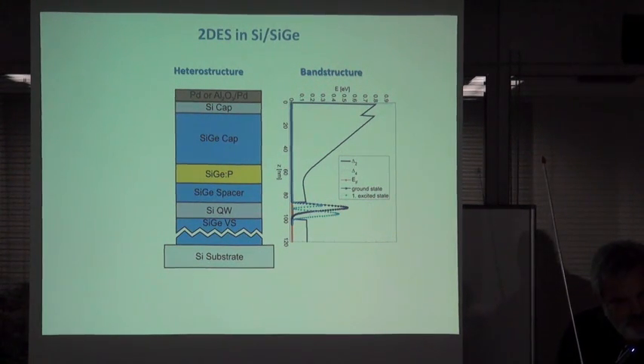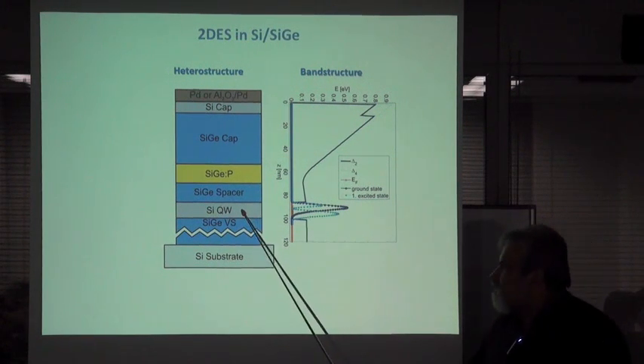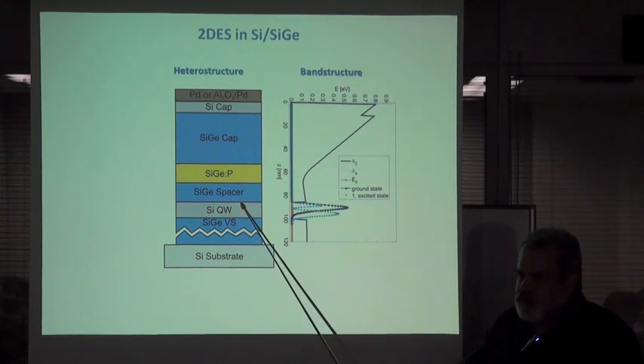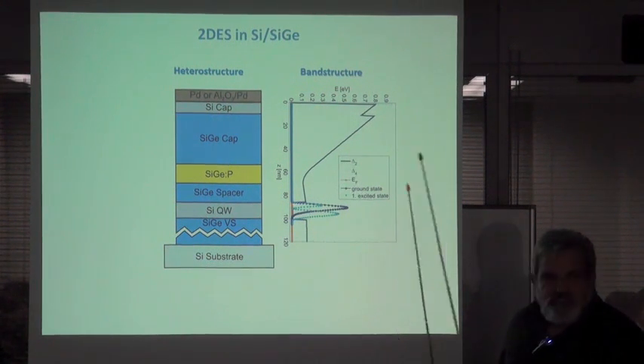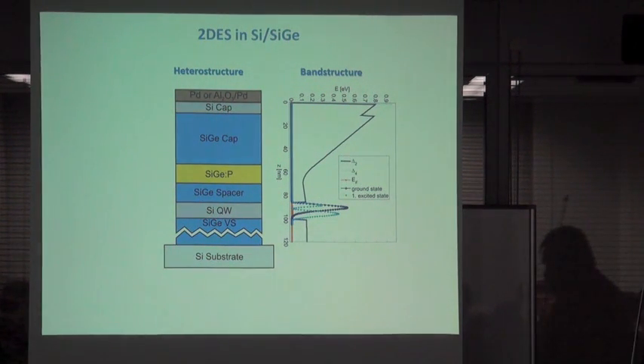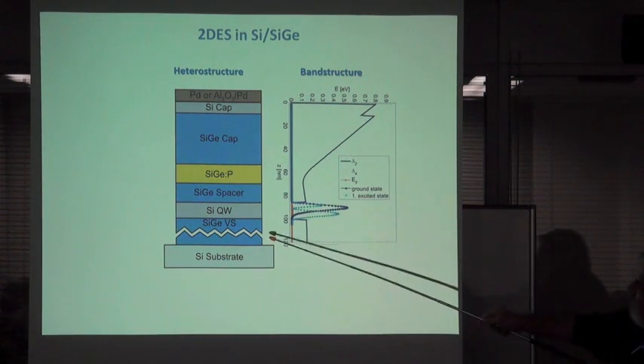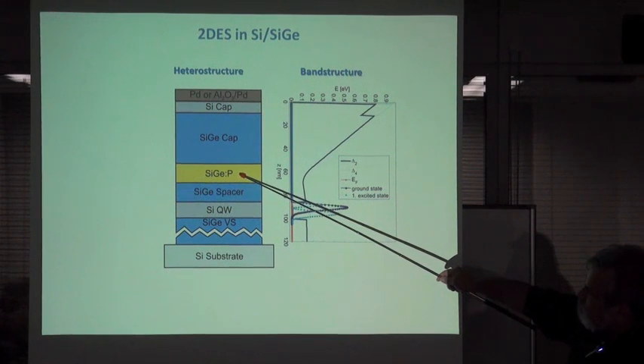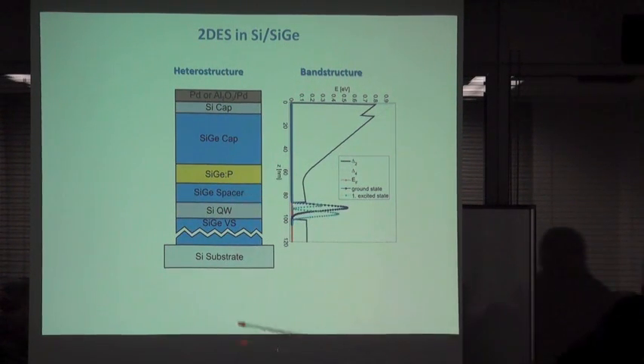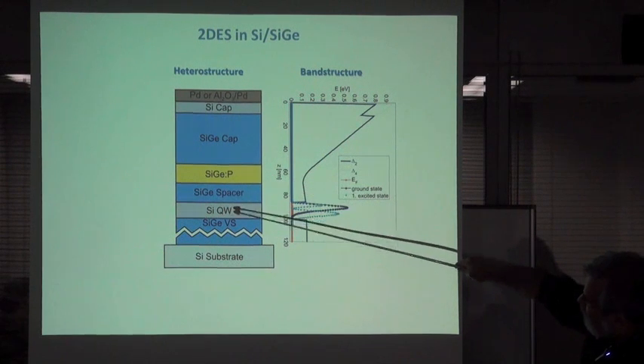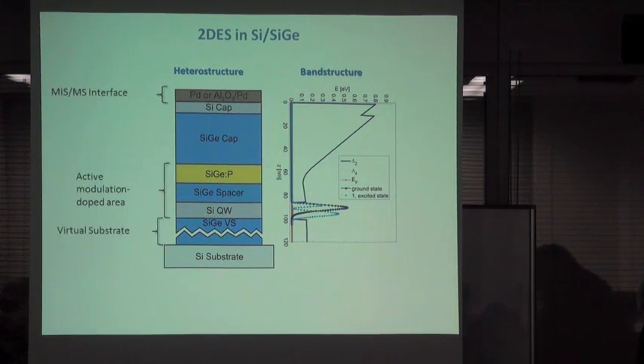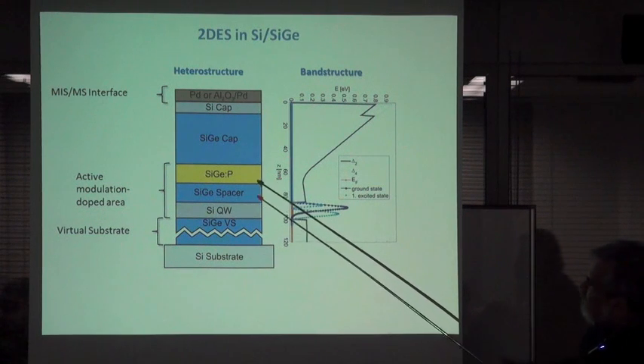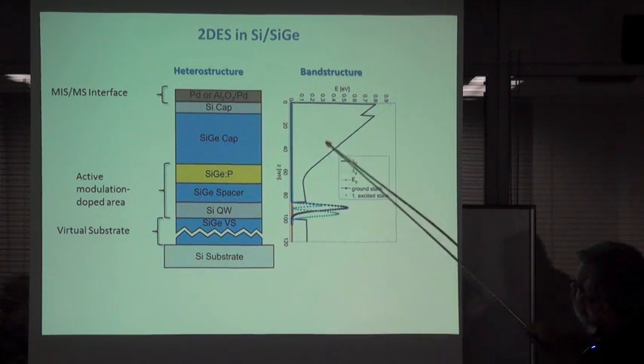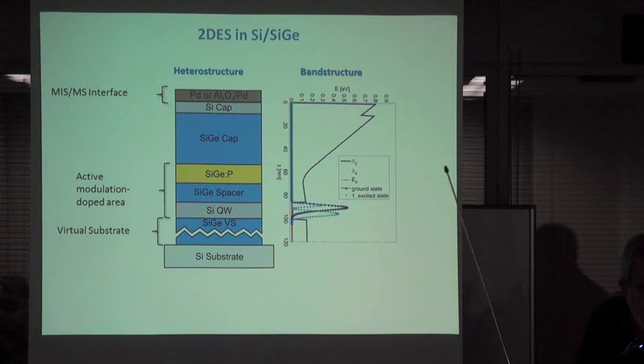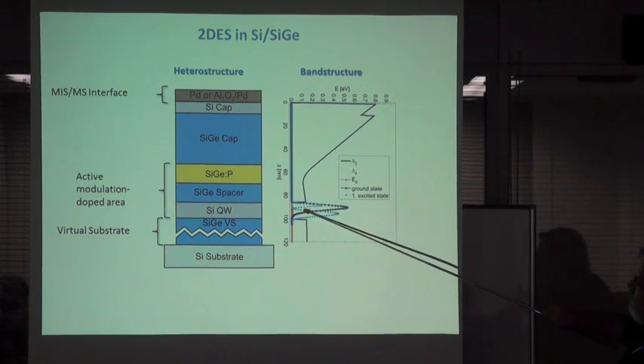And this is a Physical Review letter which showed for the first time that in tensile strained silicon you get a splitting of these valleys and you get a strain-induced two-dimensional electron system. And still we use a very similar structure. You can then, for example, introduce doping. We use phosphorus, other people use antimony as a donor here, and then you get an electron channel in this two-dimensional electron system. So what we have is basically a Schottky diode, a Schottky type transistor. We put the metal on top, and then we can tune the electron systems.